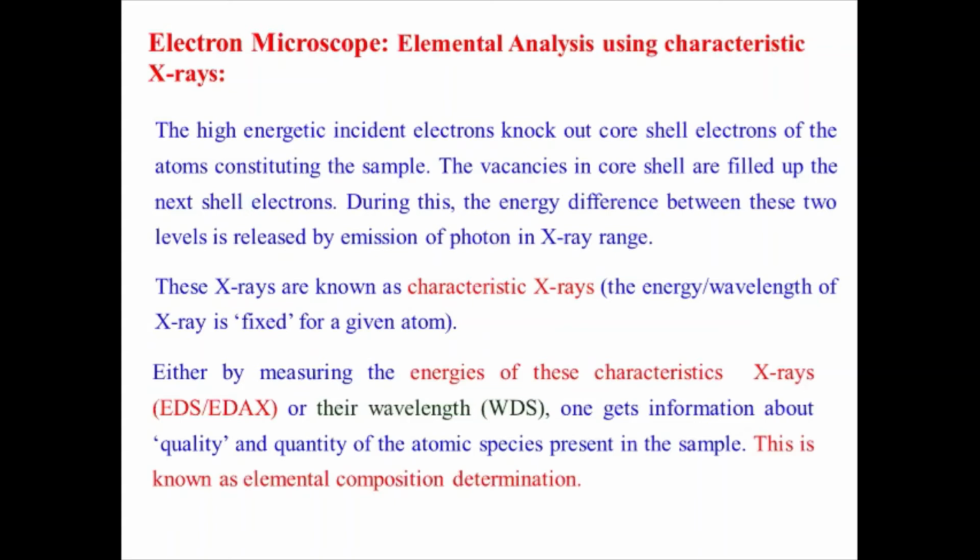With a note of caution, elemental analysis and chemical analysis are very different. Chemical analysis does not mean only the elemental analysis. Chemical analysis has a deeper sense of understanding in terms of what is the oxidation state of that atom, what is the chemical environment that atom will offer to the surrounding.